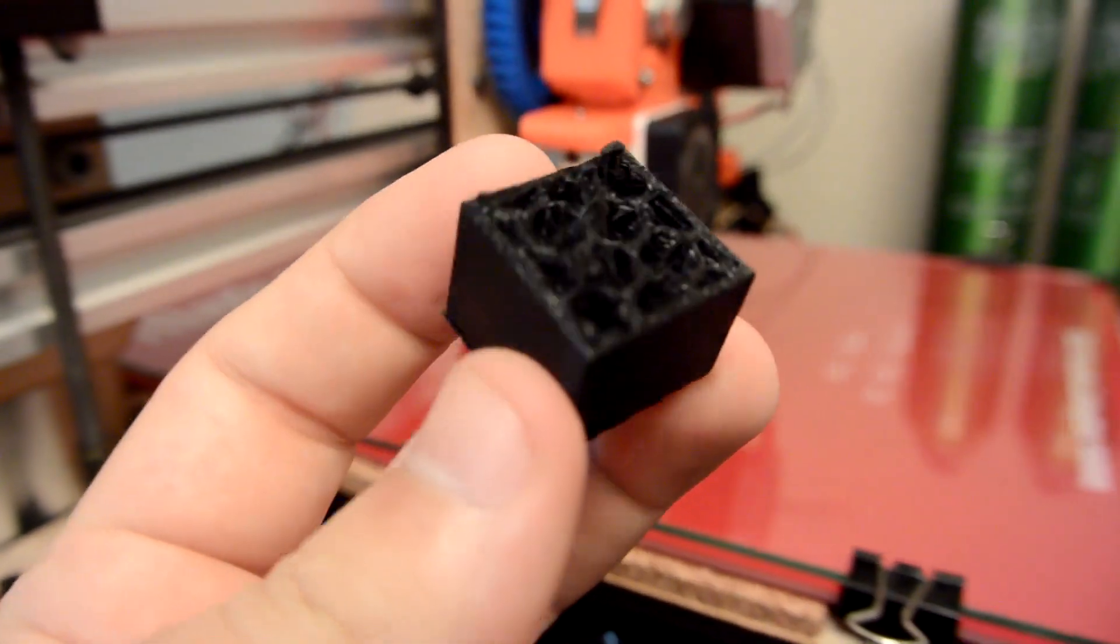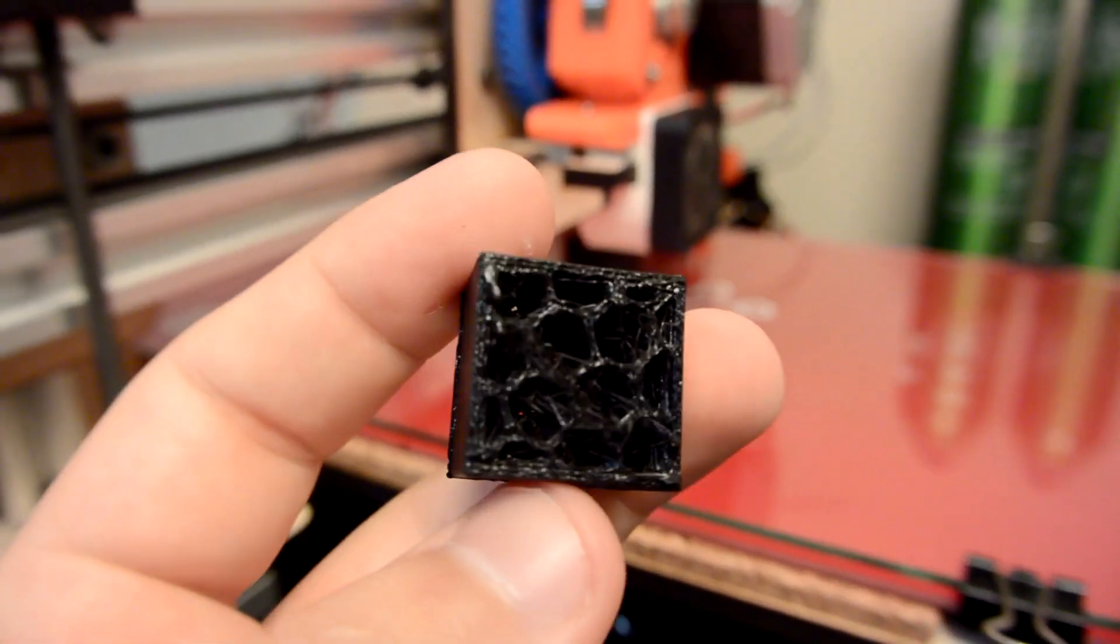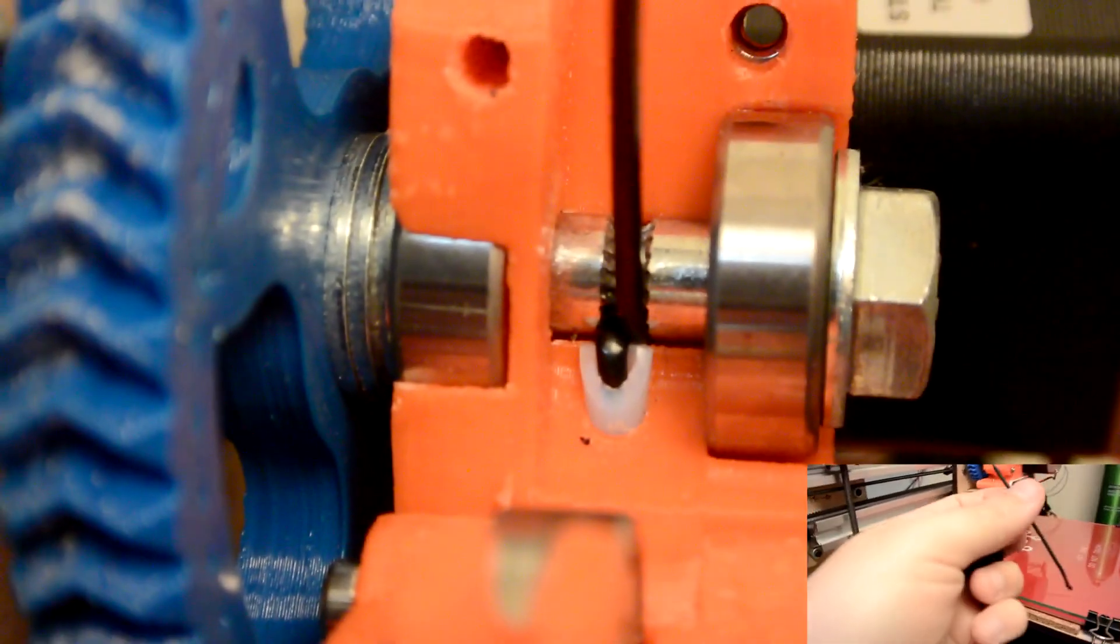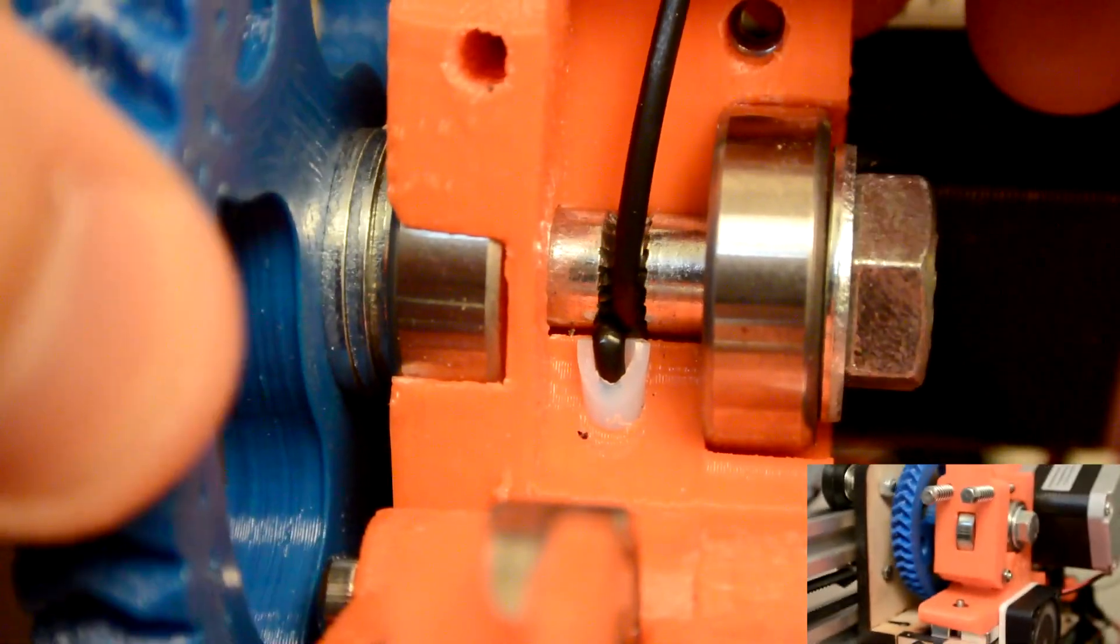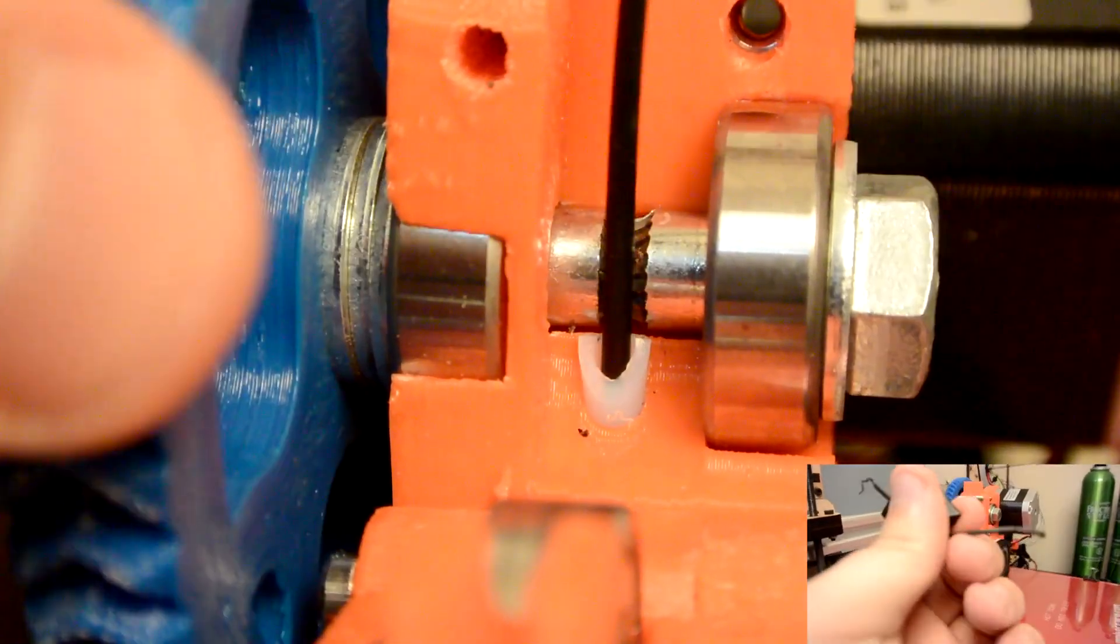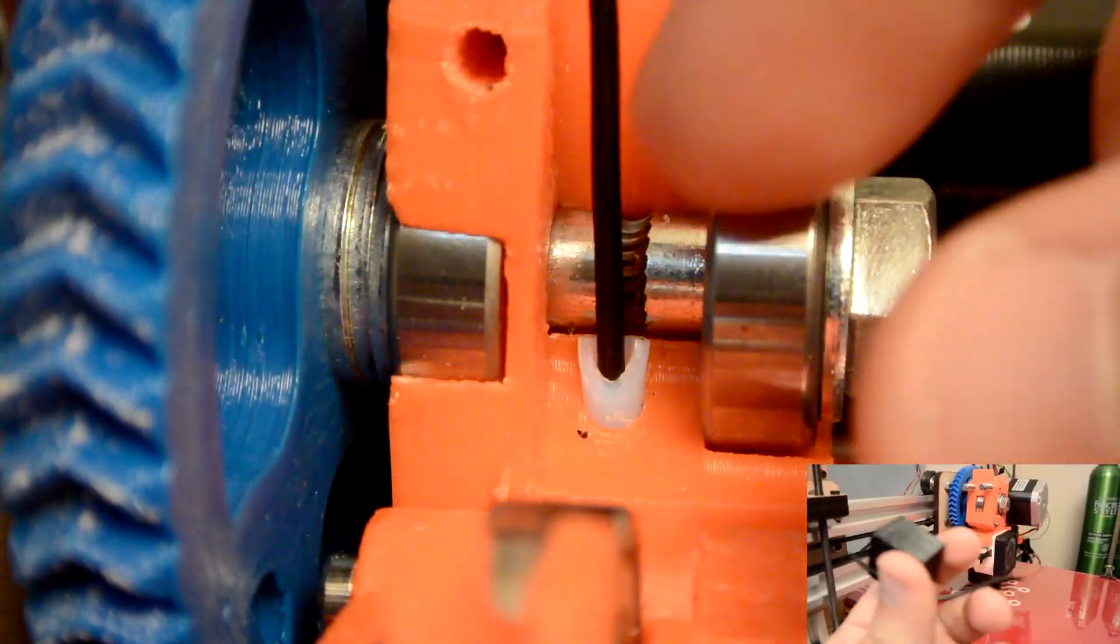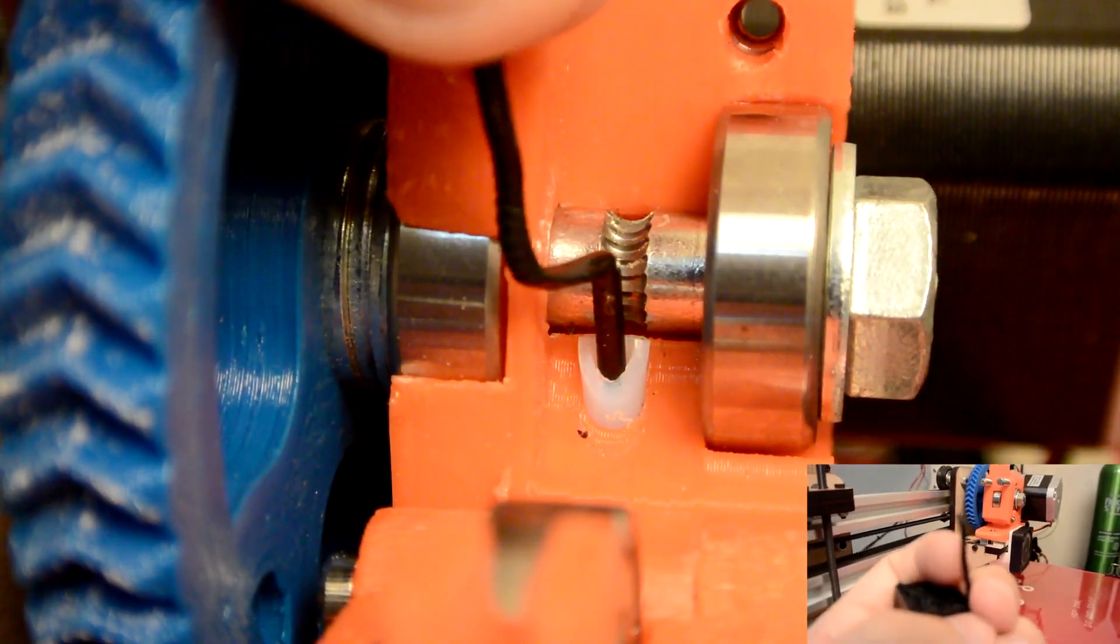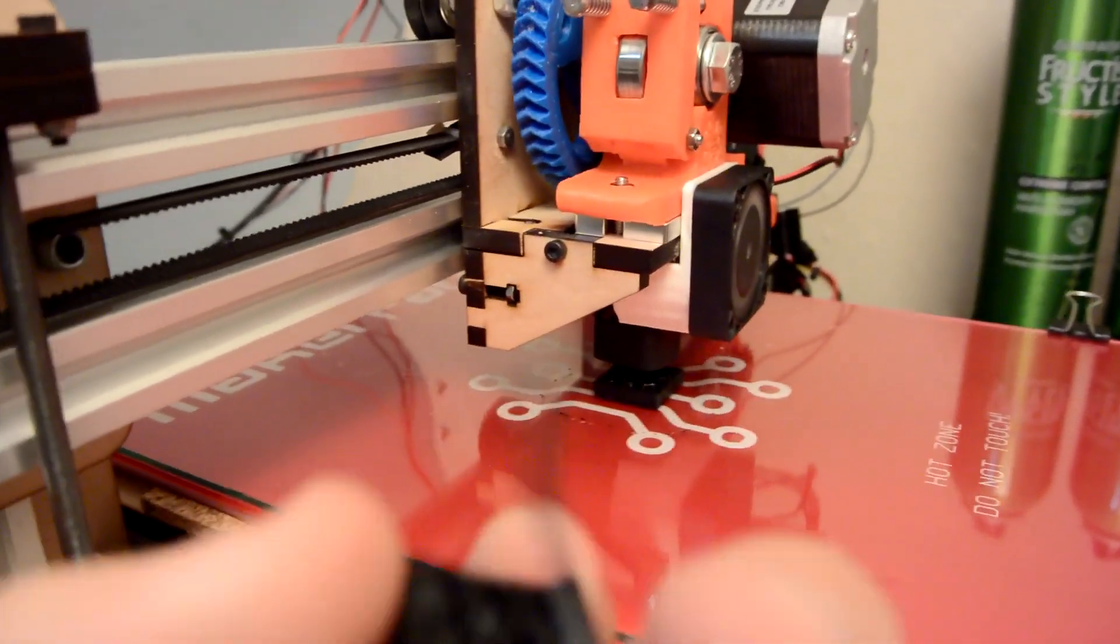So the first one failed about, I don't know, 75% of the way through. It turns out that this stuff is really difficult to print. And some of the filament got jammed in the hot end. So after the drive bolt, where I added the Teflon tubing to kind of prevent that, apparently there's still enough space for this to get sucked under the hot bolt and get into the space underneath there. So I'm going to have to bump up where the liner is and really push it against the hot bolt so there's absolutely no space for this filament to get jammed in there.